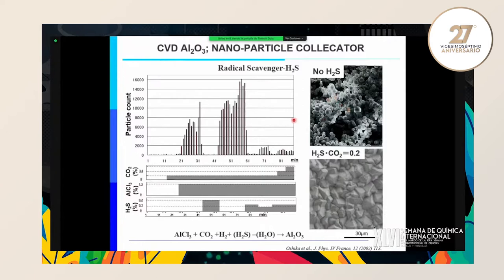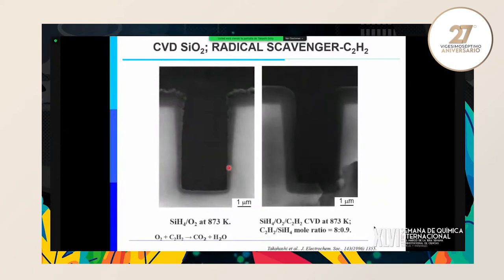Hydrogen sulfide is called a radical scavenger in alpha alumina CVD coating. So H2S is thought to eliminate nanoparticles in the gas phase, which become the nuclei in the gas phase. In the case of silica for IC circuits, a very flat SiO2 film should be coated on silicon by CVD. However, it is very likely to deposit nanoparticles on the silicon surface. It is very bad for preparing IC circuits.